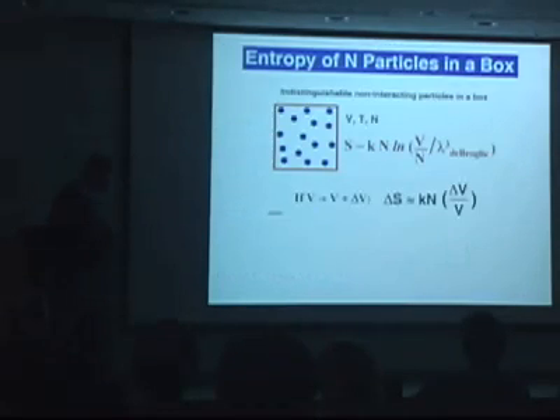In addition to enthalpic interactions, or just interparticle interactions, you also have entropy that contributes to the free energy. And the entropic contribution during self-assembly of particles can be rationalized on the basis of non-interacting particles in a box. The entropy of this system will be dominated by translational and rotational degrees of freedom for each particle. And essentially, it will be related to the volume per particle, the free volume per particle to move.